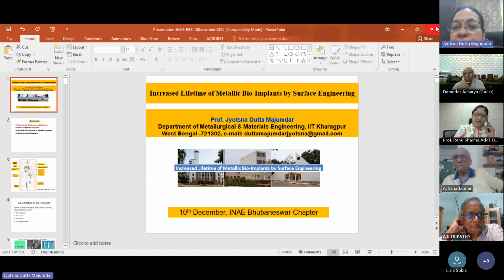Gas nitriding certainly could be a better choice, but it takes a lot of time and is a very lengthy process. So we tried to replace it using laser processing, laser surface nitriding. With laser surface nitriding we could also avoid the white layer formation observed in normal nitriding, because the structure is not a monolithic nitride layer, it is a nitride dispersed layer. The dispersion of nitride was beneficial in improving the wear resistance to a large extent without sacrificing the toughness.